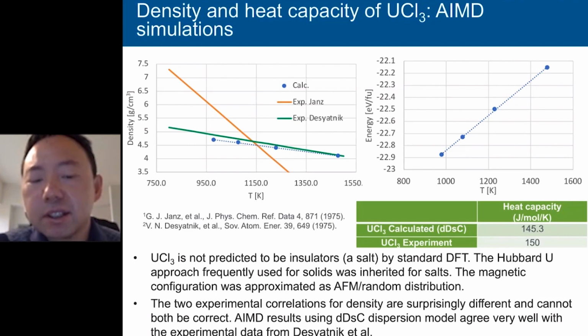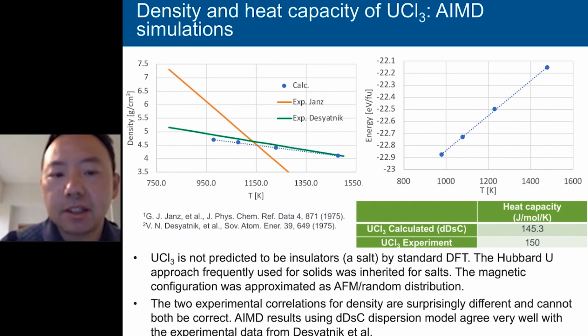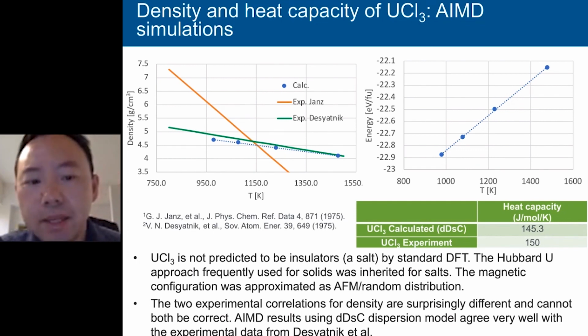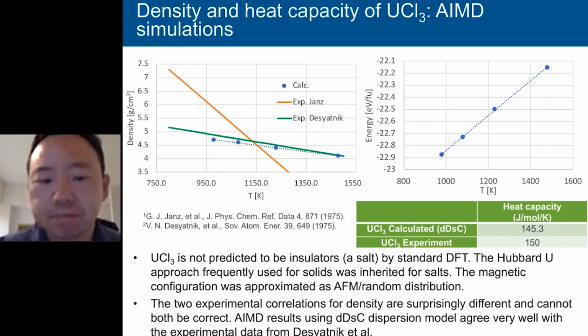The right figure shows the energy calculated as a function of temperature. If you fit a line through these 4 points, you calculate the slope. That slope gives you the heat capacity. And again, you can see that the Ab-Initio calculated heat capacity also agrees very nicely with the experimental data. So this is a cool example showing where the Ab-Initio MD can be used to help us judge the quality of different experimental data when they don't agree with each other.